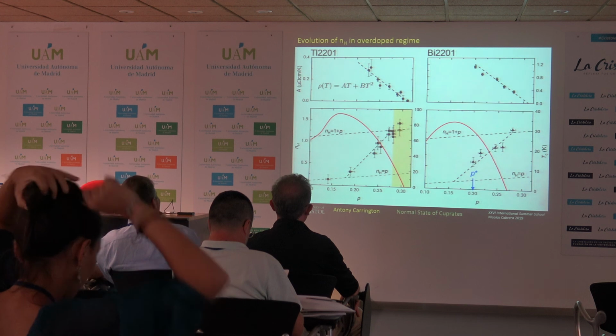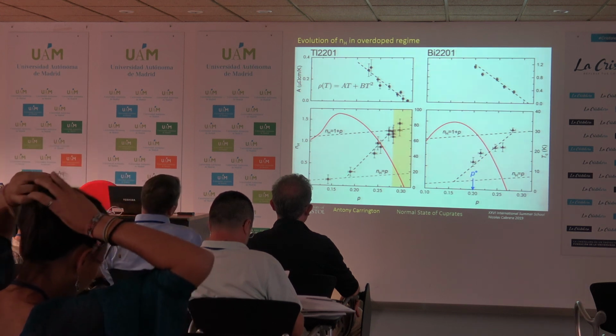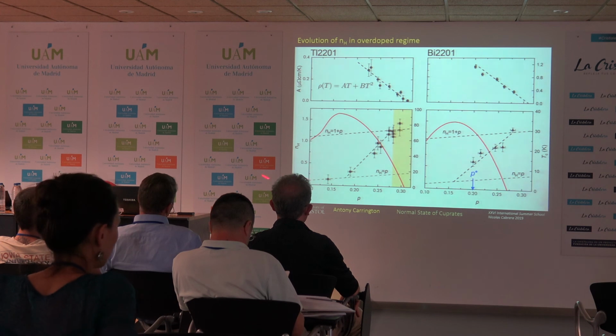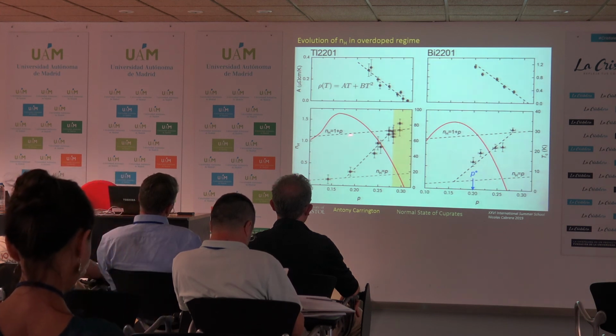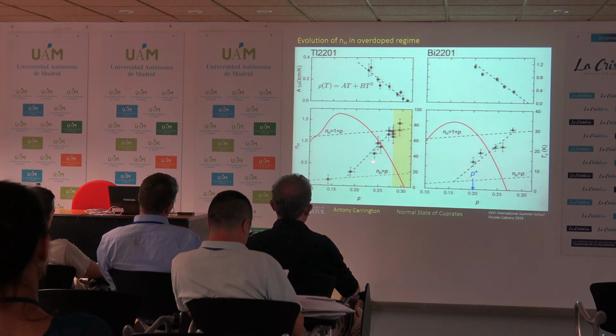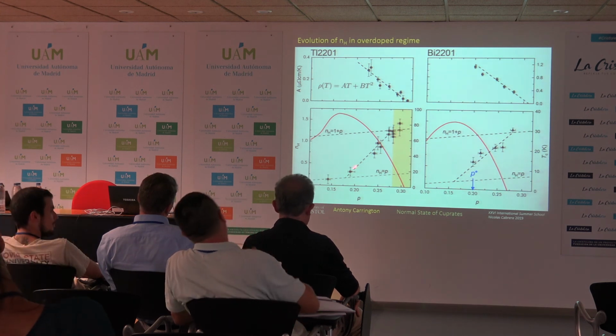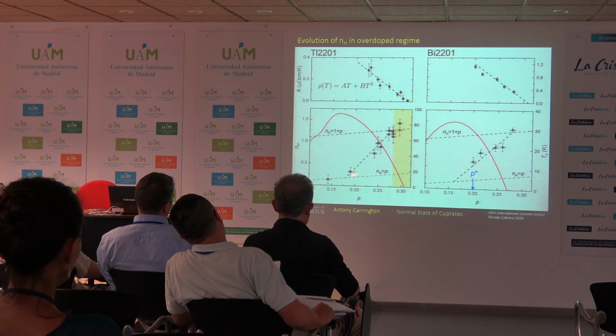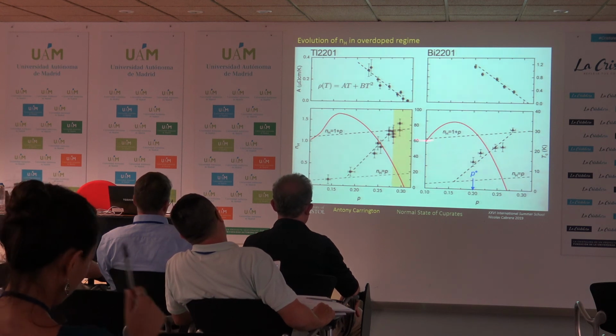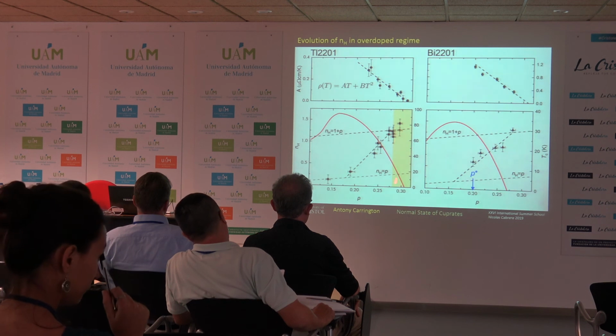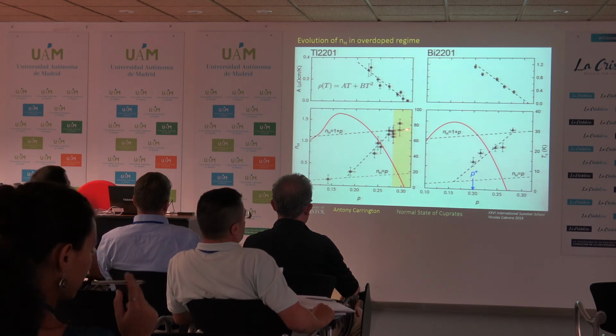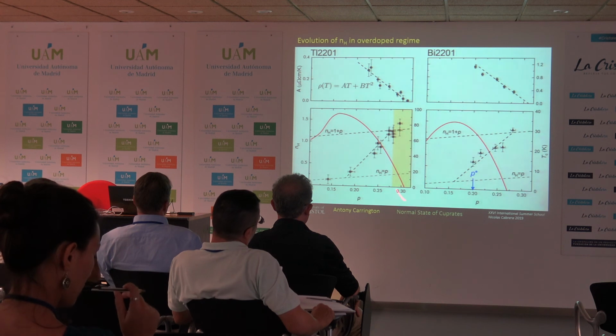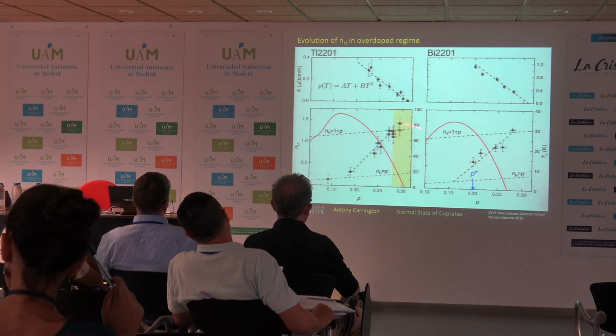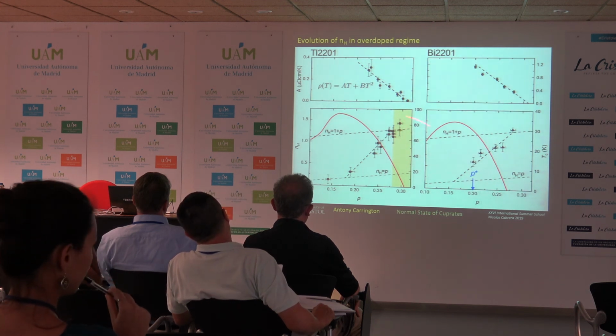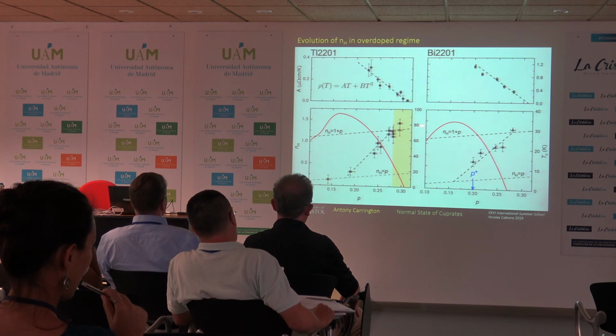Okay, but when we repeated this for other dopings, what we found was this. We don't see an abrupt change at 0.19, but rather a very slow change that occurs over quite a large proportion of the phase diagram. And it only really reaches 1 plus p right at the edge of the superconducting dome. In fact, in exactly the same region where we can see quantum oscillations. So this yellow region is where you can see quantum oscillations. This is where the Hall number equals 1 over ne, and then it quickly falls here.